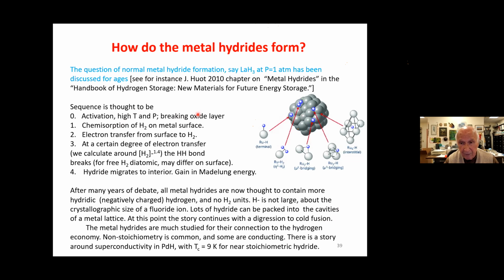And what is thought to happen in step 0 here is that first you have to get the surface clean. The reason you can cook in aluminum pots is your aluminum pots are covered with a rock-stable aluminum oxide layer that protects them from anything, but you better not scratch them too hard because you will expose the aluminum, which will react with the iron on the stove. So that, anyway, you have to first clean off the surface. With high temperature and pressure, you sinter the particles, break the oxide layer.